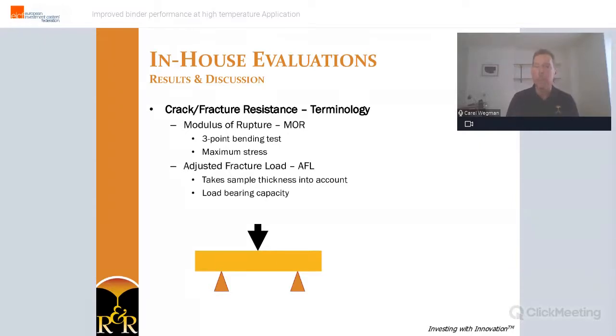Now, shell thickness is normally increased in two ways, by using more total coats or by applying thicker individual coats. A shell material with a high MOR would allow foundries to cut coats and still maintain an adequate load bearing. Therefore, increasing MOR or AFL is a generally accepted way to improve the resistance to cracking and fracture. That being said, internal R&R research has proven that the shell permeability also has a big effect on its capability to resist wax expansion forces. But maybe this is something that we have to explain in detail during another presentation.